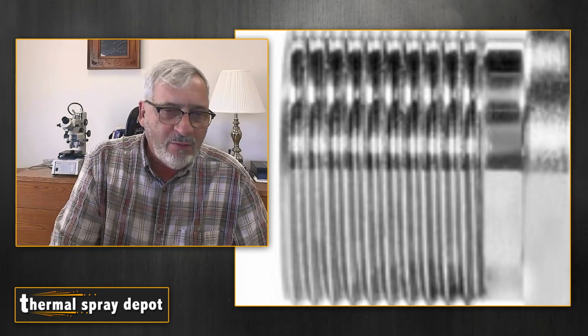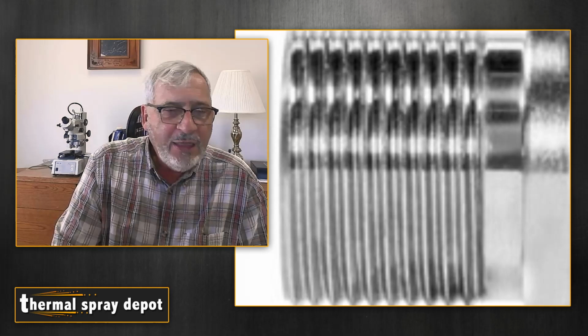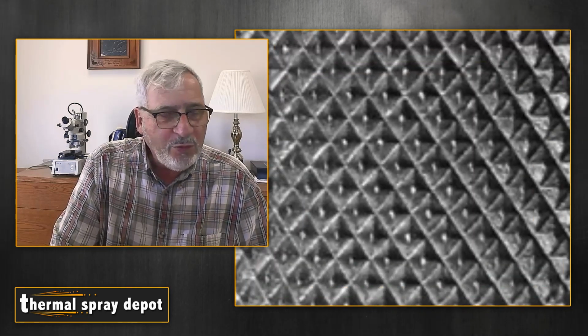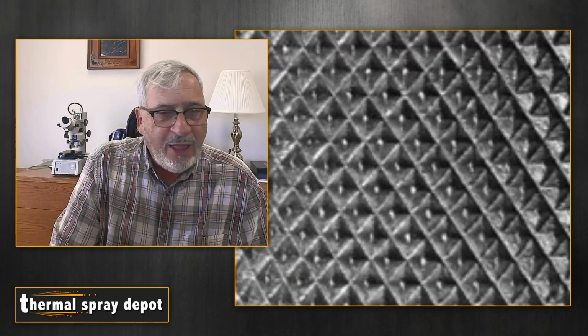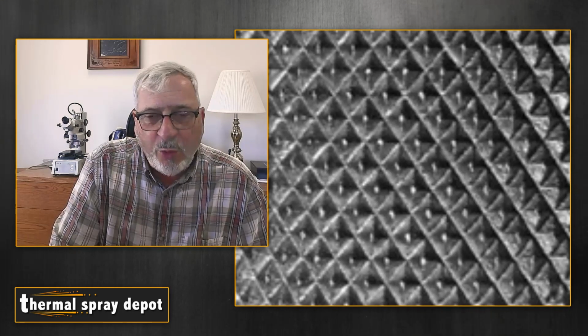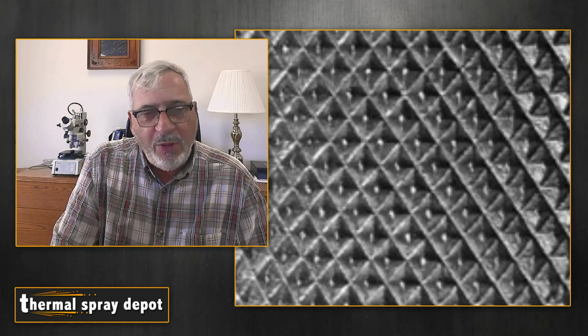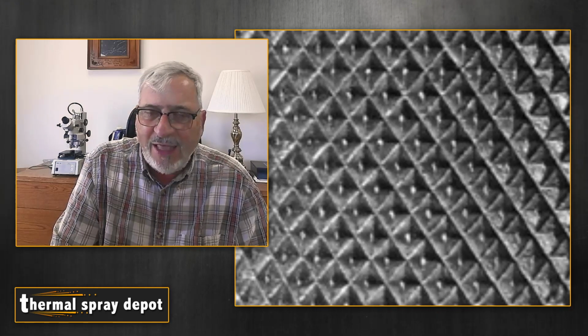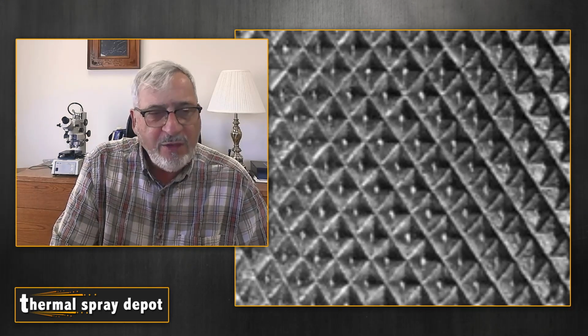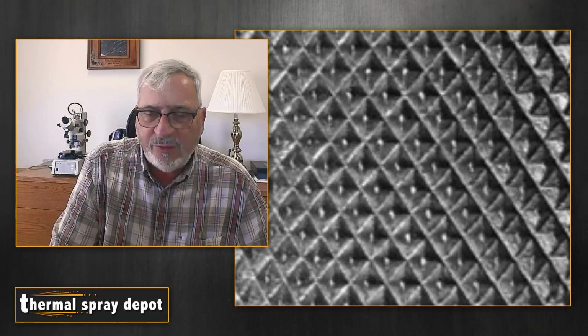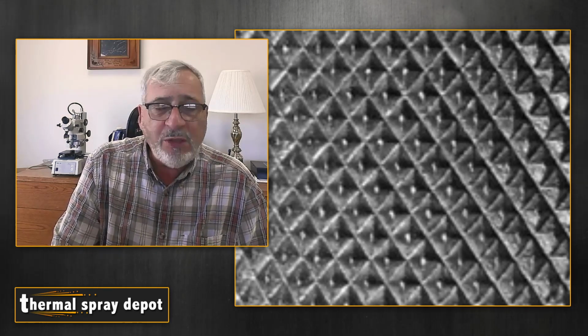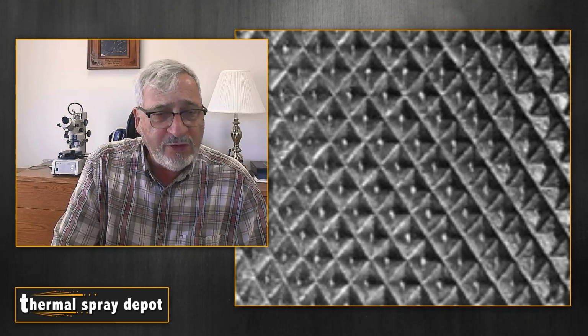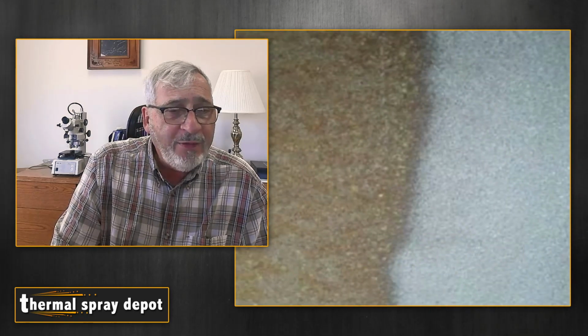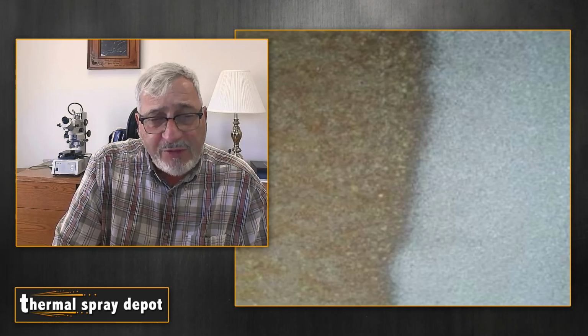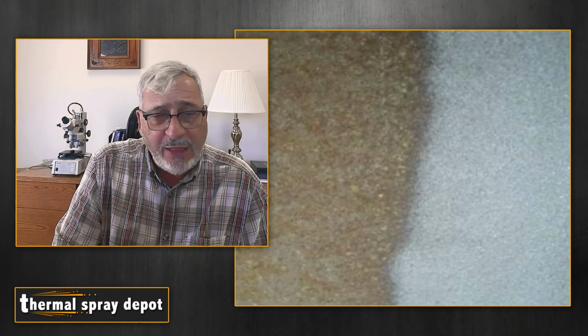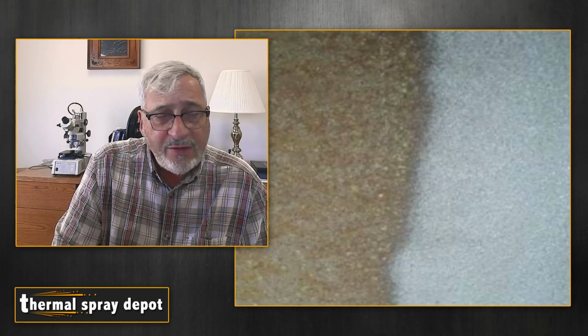And there's a second, again old school, way of doing it, and that was using what we call knurling, which would be our next picture here. Again, this is a little bit better and there's more surface for it to hang on to. But the surfaces that are knurled still have a very smooth surface to them. That's not the best surface for thermal spray to stick to. What you really want to do is a grit blast on these surfaces, which would be our next picture. This is a little difficult to see, but on the left side is a plain carbon steel that was not prepped. On the right side is a grit blast surface.